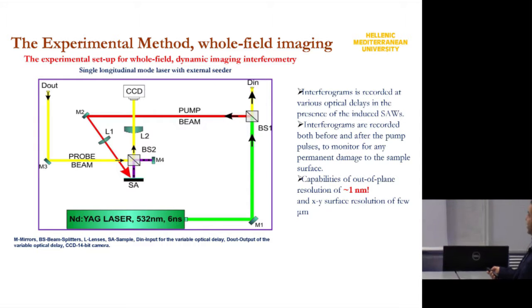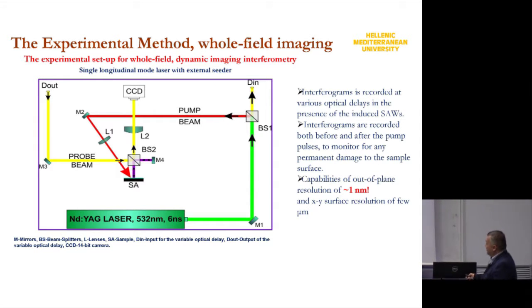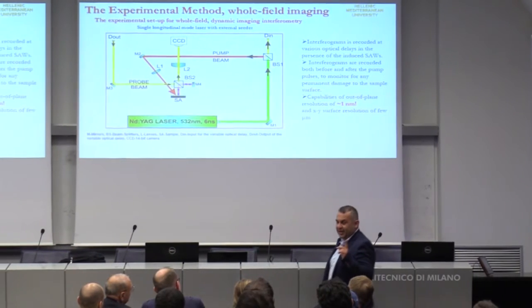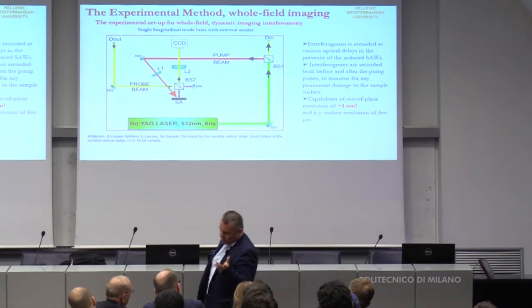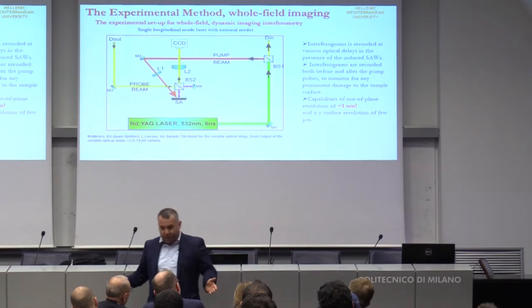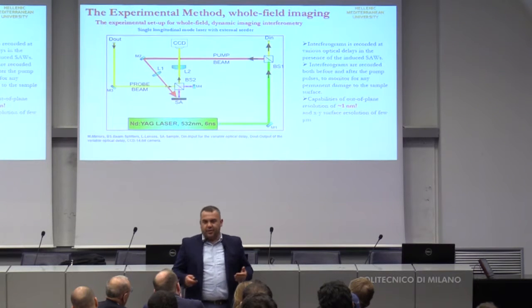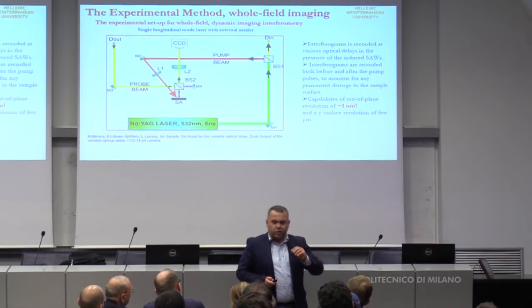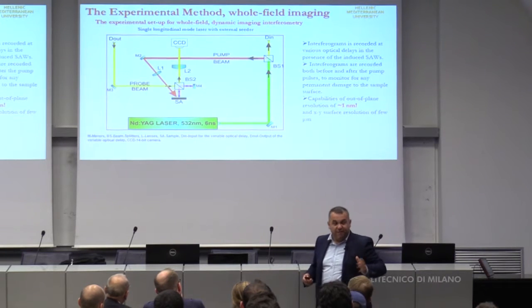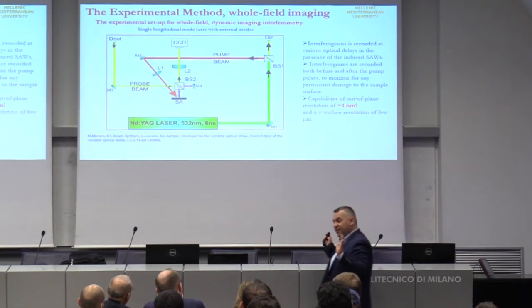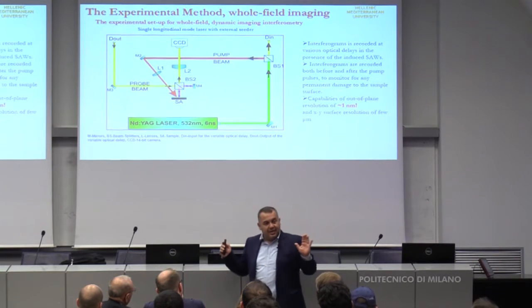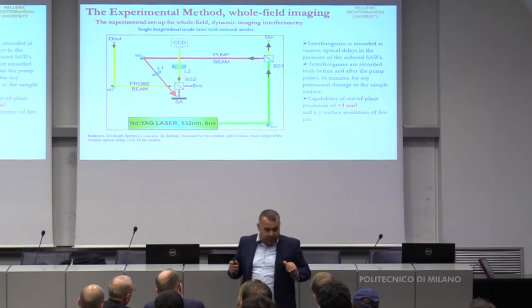For example, here we have a nanosecond Nd:YAG laser with which we can pump the material, and then we can observe with a phase interferometer, but these lasers must be single longitudinal mode lasers. It's a bit crazy: a pulsed laser and single longitudinal mode. The technology can do that more or less with an external seeder, where we can really have more or less one mode of vibration of the laser. So we have a very good, let's say, plane wave of a nanosecond laser pulse.